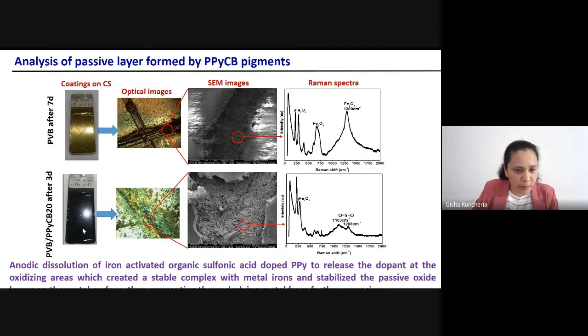And this is the conducting polymer coating. There also we made a cross cut. Both coatings were immersed in 4 weight percent sodium chloride solution. After 7 days, the pure PVB coating was analyzed for optical images. The optical images show that in the cross defect area, some products have formed. Similarly, the conducting polymer coating, after 3 days, we took it out, and optical images show this scratch is almost covered. Now we have to find out what this product formed on this cut is.